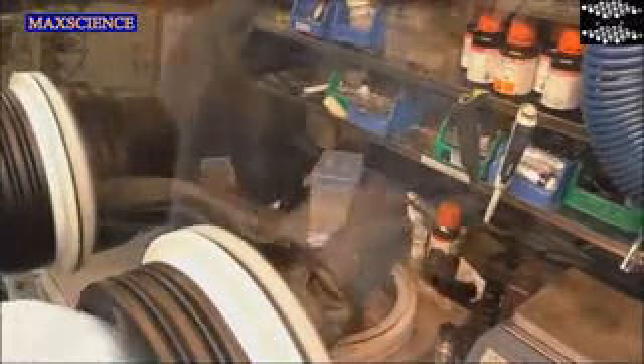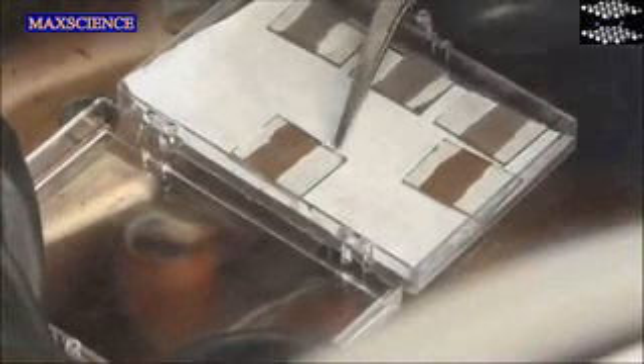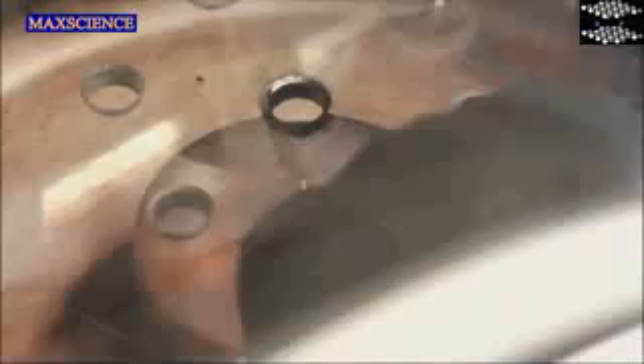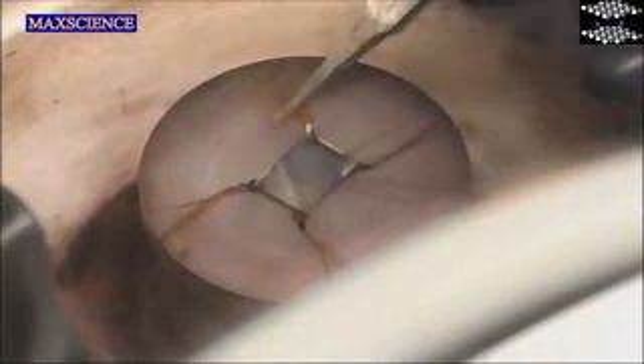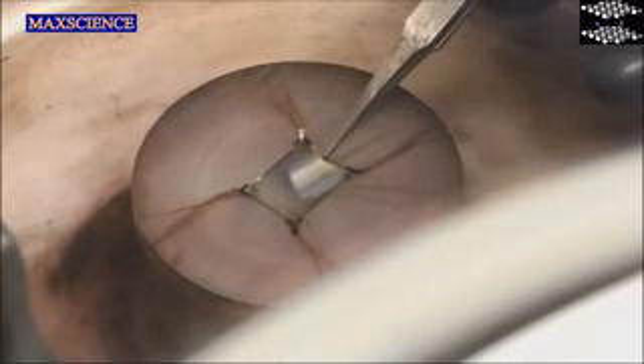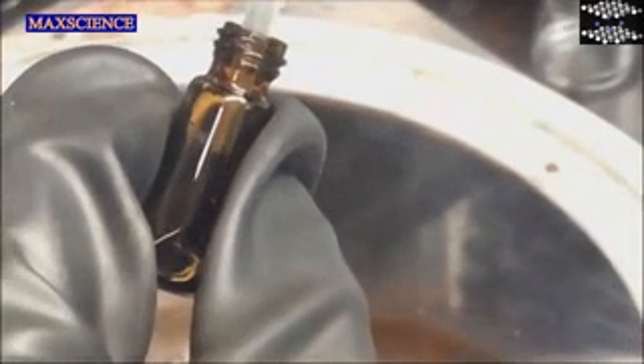Once the perovskite films have been annealed, they can be transported to a nitrogen-filled glove box where they will be coated with a PCBM electron transport layer. Place the substrate in the spin coater, making sure it is secure. Take 20 microliters of a filtered PCBM solution and dispense onto your substrate at a spin speed of 1000 RPM for 30 seconds.